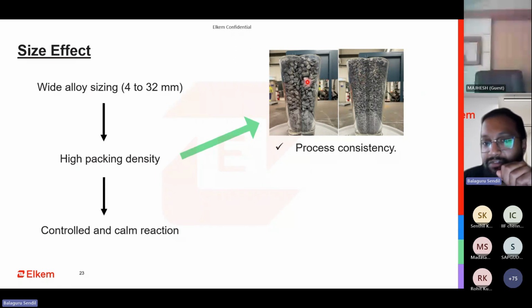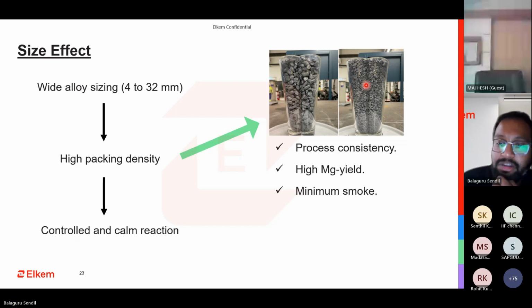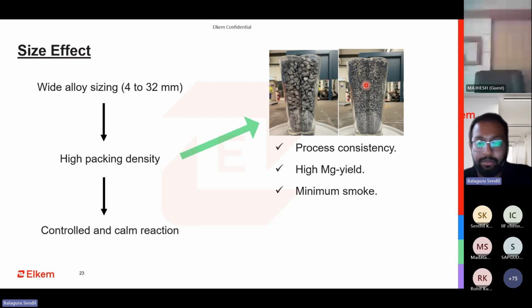Here, when you are using this sort of a size range, the way they dump it inside is again a challenge. So most of us started using automatic feeder machines. This can always create a problem of inconsistency. Sometimes it can be good, sometimes the residual Mg can be low. A smaller or a wider size range will give you a more stable process, and it will improve your magnesium yield, and it will also reduce your smoke percentage. You'll have very little smoke.